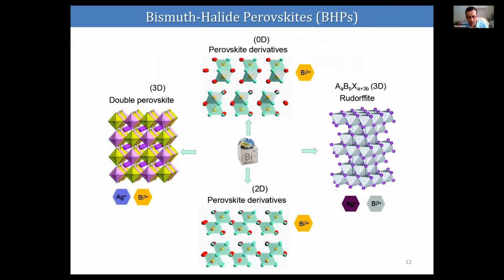The literature says that bismuth can form a variety of structures because it has the possibility to form different oxidation states, and it also has the capability to form stable complexes with many organic cations. Because of that, you can use bigger organic cations, forming zero-dimensional perovskite-like structures. We cannot say it is a real perovskite structure because it deviates from the ABX3 stoichiometry, so we call them perovskite derivatives or perovskite-like materials. They can form zero-dimensional perovskite-like materials, or with other moieties they can form 2D perovskite structures, or even double perovskite structures with cations like silver, or rudorffite-like structures. So a variety of structures are possible with bismuth halide and bismuth metal.